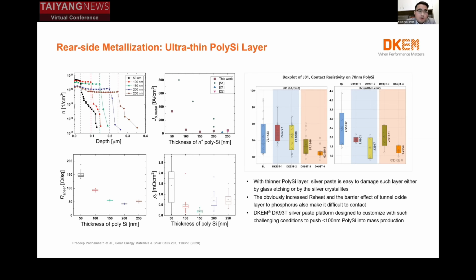So we studied what happened and what the reason behind this is. We found that with a thinner polysilicon layer, the R sheet increased significantly. This is the first one. The other thing is that the tunneling oxide layer has a barrier effect for phosphorus diffusion. You can see that in the doping profile of the polysilicon layer, the doping level dropped significantly around the tunneling oxide layer. This means the barrier effect. Those two make it difficult to contact ultra-thin polysilicon layers.